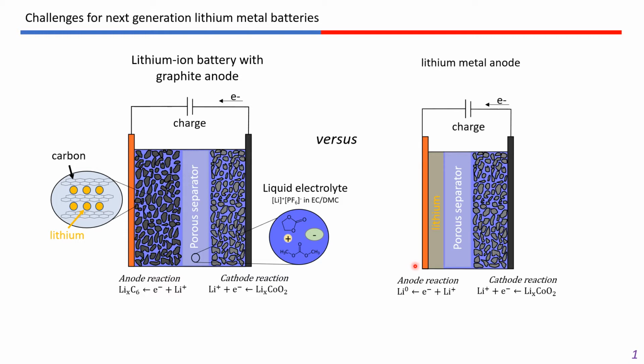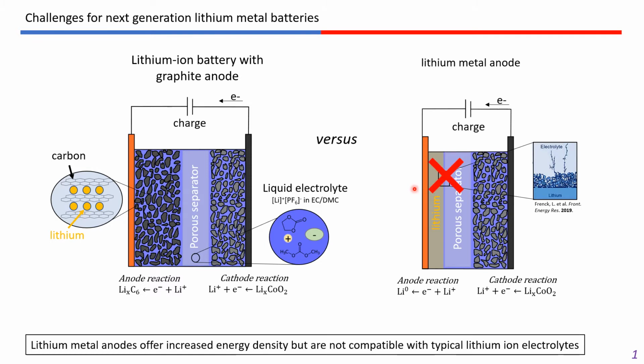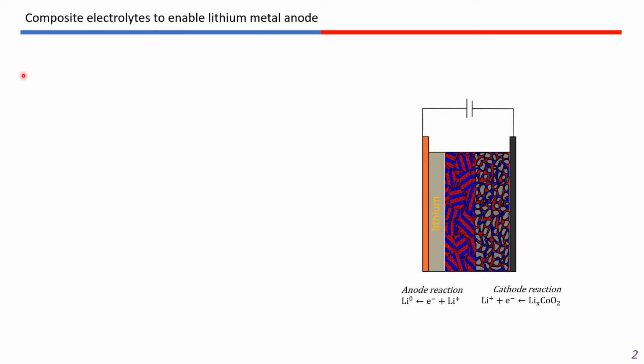of this battery. However, with traditional liquid electrolytes, this results in the formation of dendrites, which can short circuit the cell and ignite the flammable liquid electrolyte. And so, while lithium metal offers increased energy density, it is not compatible with typical lithium-ion electrolytes. One potential solution to this problem is to use composite electrolytes to enable the lithium metal anode.